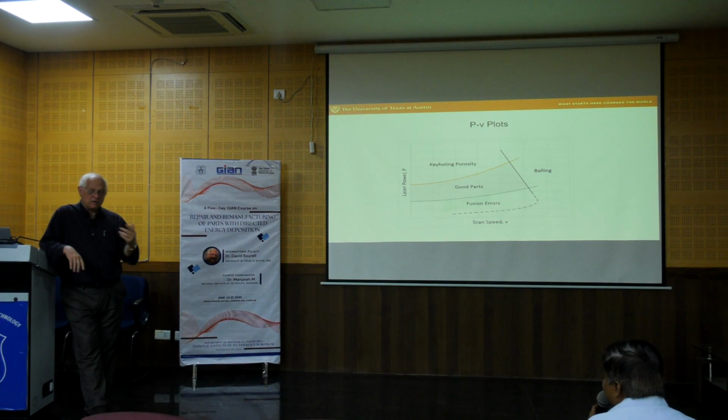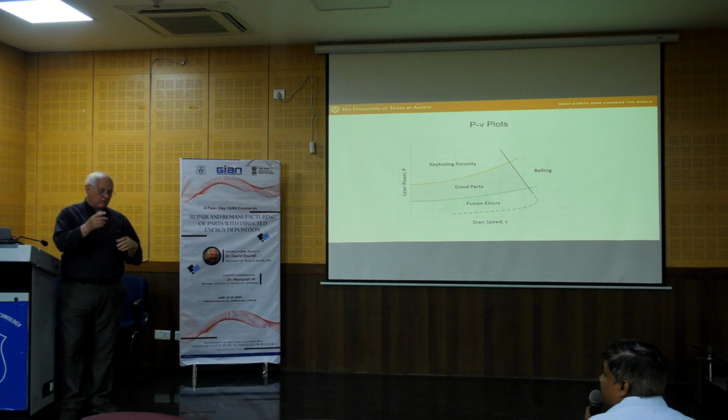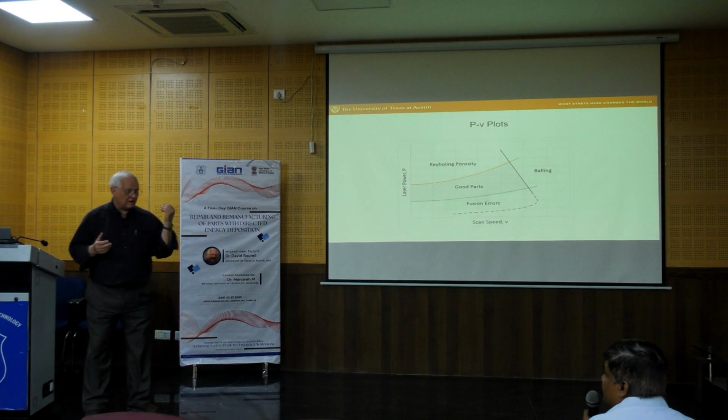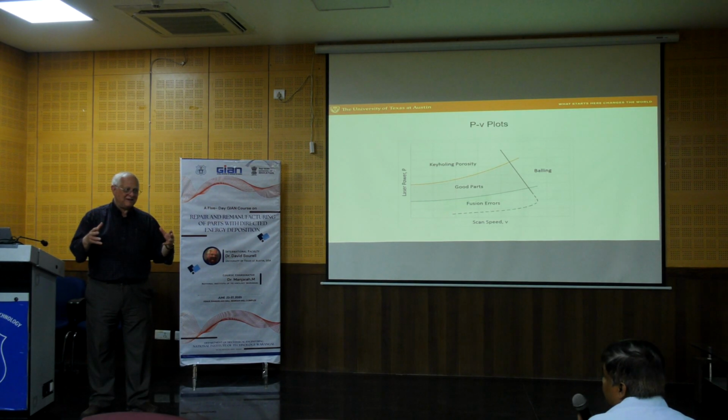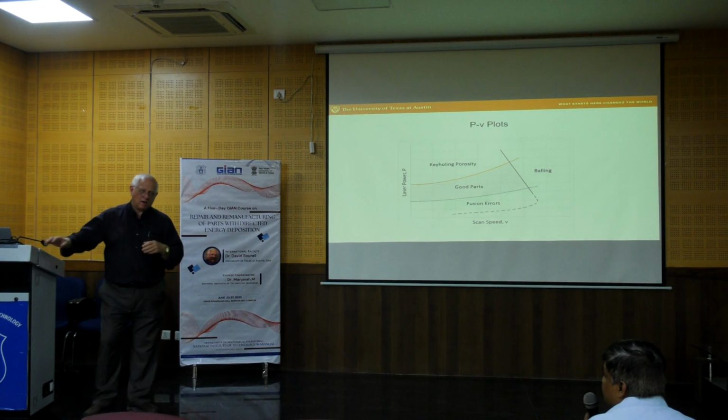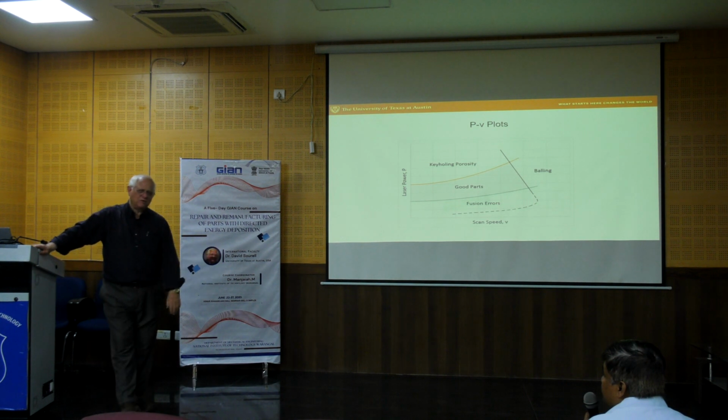I can tell you industrially, what they do is once they have that information, at least with Harvest Technologies, where David Lee was, the way he would optimize is he would do full chamber builds once he thought he had a good process. Full chamber builds could be quite expensive in terms of the feedstock, but he would do that. I think he told me once he went through maybe 300 or 400 pounds, so maybe 200 kilograms of powder just to dial in the material.